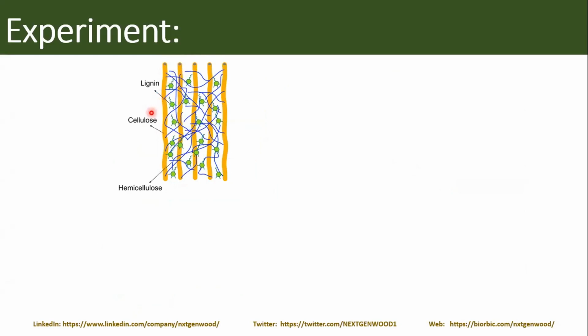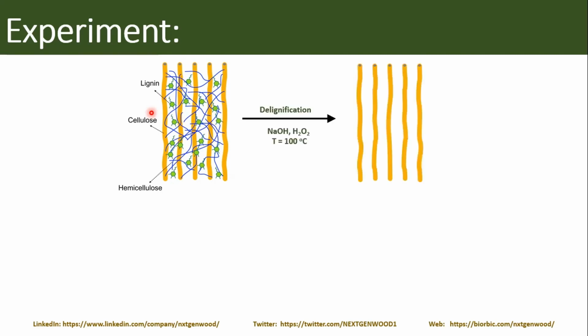And in a normal natural piece of wood, this space between these fibers is always filled with what is called lignin and what is called hemicellulose. So lignin is a natural polymer. Hemicellulose is also some sort of fibers. Altogether, it makes the structure very mechanically stable. And at the same time, altogether, it makes it not interesting for us as a membrane. There are some big scale, micro scale channels to transport liquid in the wood, but that's not what we're looking for. So that's why we need to make some chemical treatment, which is called delignification.